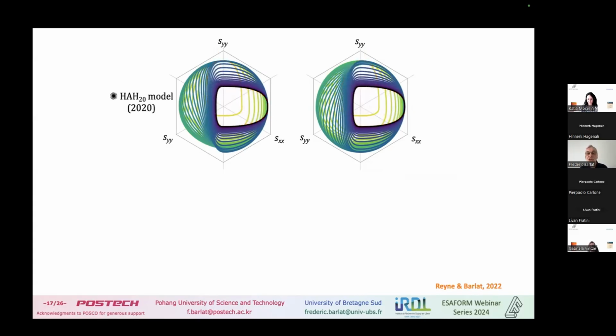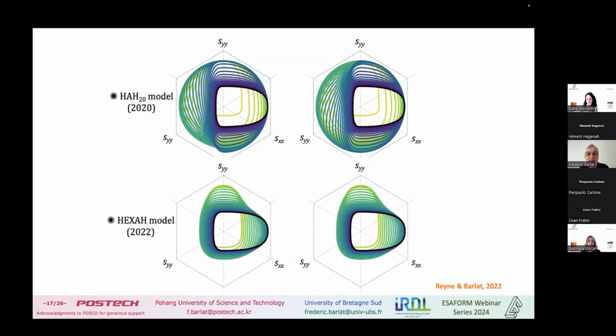But when you look at the shape, it's slightly different, very slightly. If you look at the bottom here, slightly different here, and the size, because all those lines represent the evolution of the yield surface. So one line represents one evolution. You see those lines here are more dark green, more in this direction, whereas here they are a little bit different. And so it's kind of a singularity here. And this is the reason why HEXAH was developed, because we don't have this singularity.